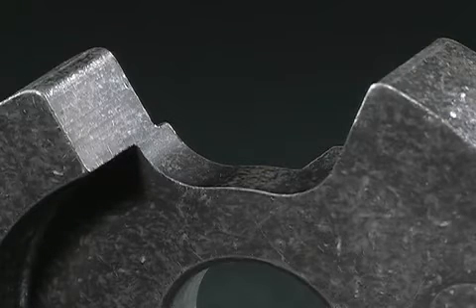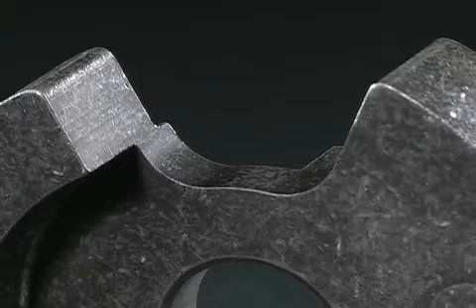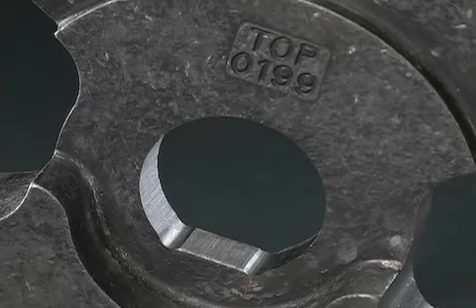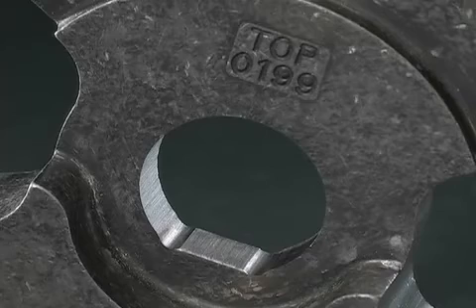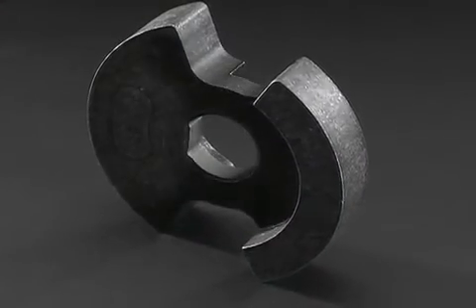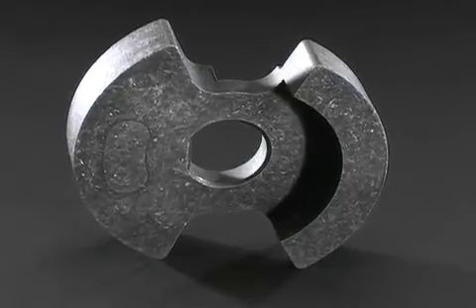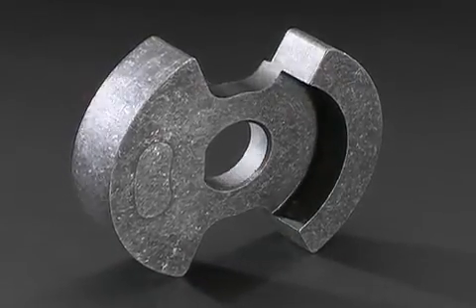It replaced a 2-piece design that required machining the bolt and threaded holes in addition to separate tooling and presses for both parts. The customer conducted fatigue and vibration testing and reports double the fatigue performance compared to the previous 2-piece version. What's more, assembly of those 2 pieces required the use of thread-locking fluid, which contains volatile organics. Eliminating this fluid through the 1-piece design is an obvious sustainability benefit of PM.